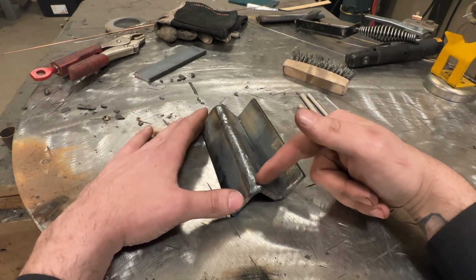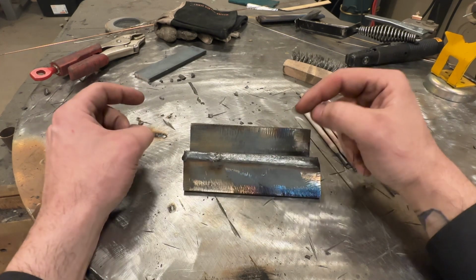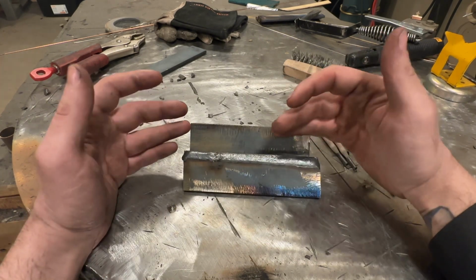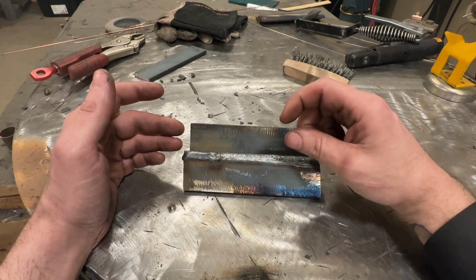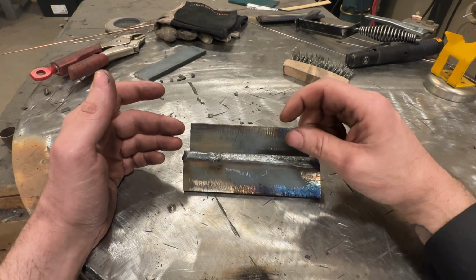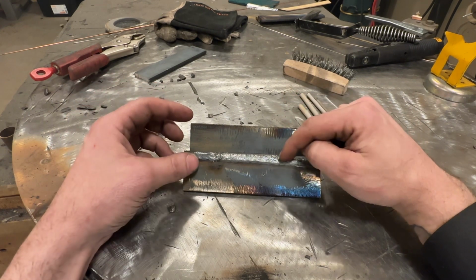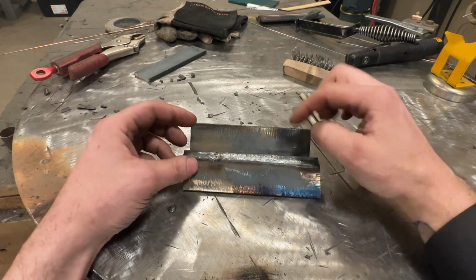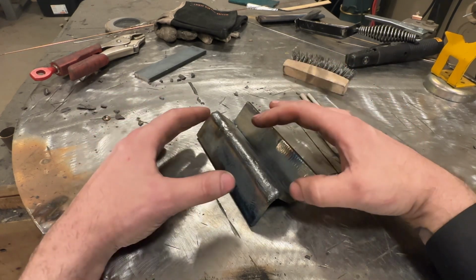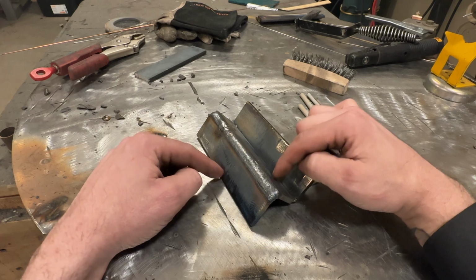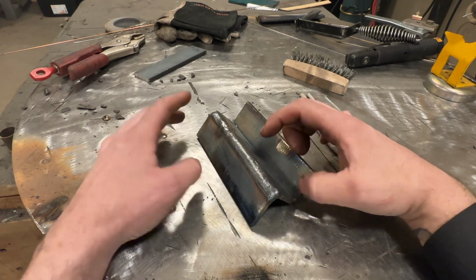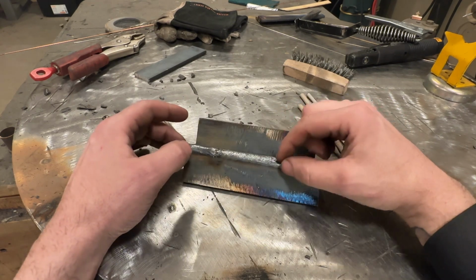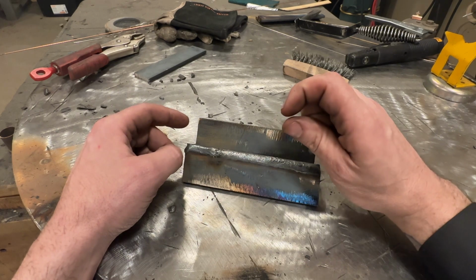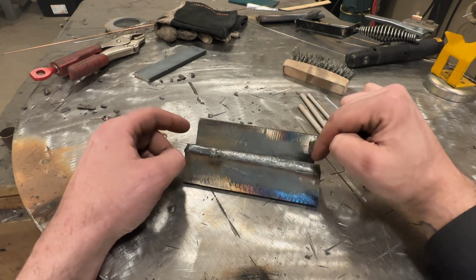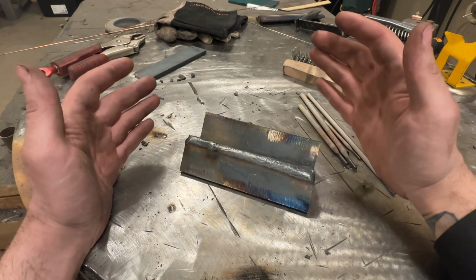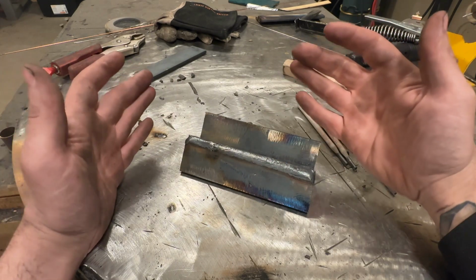So in a case of this where we just ran these 5/32 rods at about 170 amps, our weld is probably a little bit over, if not just, a 1/4 inch thick. So the weld thickness is the same as the base material. So in theory, if we were to stress this, odds are the weld would not fail. It would bend. It is as thick. Now, if we had a little 1/16 thick weld only on the inside, well, what's going to fail? Of course, the weld, because there's no reinforcement.